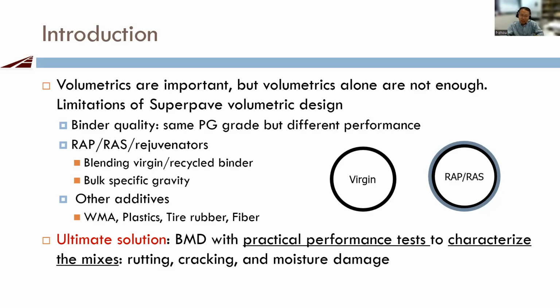And another thing is about other additives, warm mix additives. Most recently, people are using plastic, tire rubbers, and fibers, and maybe some new additives in the near future. So the current volumetric system really cannot consider all these factors well enough to address them. So the ultimate solution is balanced mix design. We consider volumetrics, but we are also using practical performance tests to characterize the mix in terms of rutting resistance, cracking resistance, and moisture damage. So that's why we really need the balanced mix design, employing performance tests to characterize the mix. It's not just volumetrics alone. So that's what balanced mix design is about.